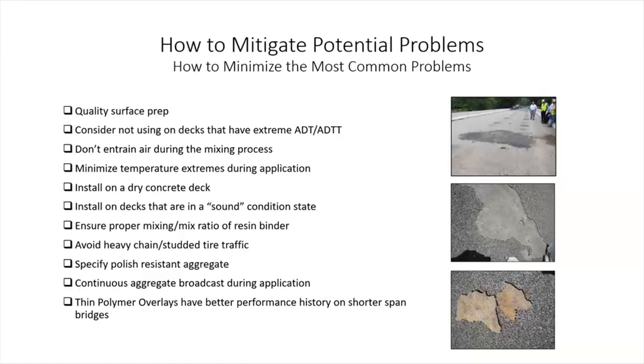Make sure that you don't have really heavy truck traffic. You may get good life cycle out of your thin overlay with very heavy traffic, but it's a consideration. Don't whip air into the resin. Keep the temperature range. I'm not going to tell you the range. There's a lot of good guidance out there, but conservative is better. Keep your temperature ranges more conservative, and you're going to have a better chance, especially in wet, really cold climates. Make sure your deck is dry. Make sure the deck is sound and in good condition. We talked about mixing. We talked about heavy chain and studded tire traffic.